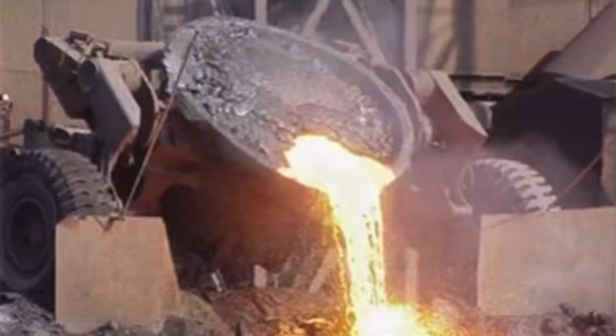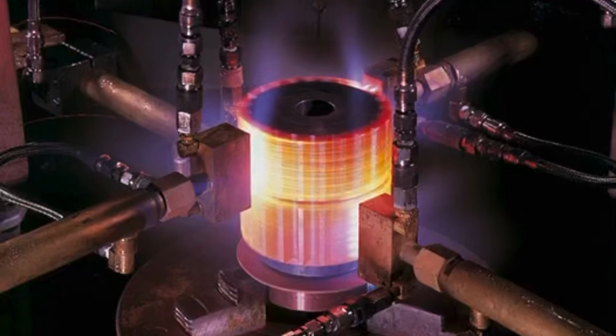Some of the steel used to make rail lines is hot rolled and then allowed to cool naturally, which is a long process. This makes for a strong steel with low amounts of brittleness. Other steel is cooled quickly with water sprays after the material was heated to over 800 degrees Celsius, which is similar to the quenching form of heat treatment. This second method of heating steel makes it much harder but more brittle due to the rapid quenching of the outer layer of material that causes a stiffness within the bonds of the steel.